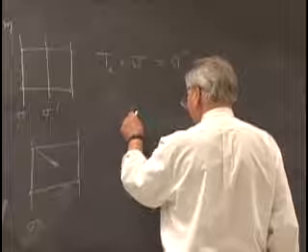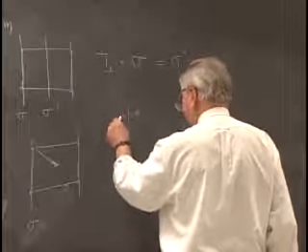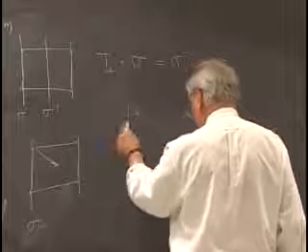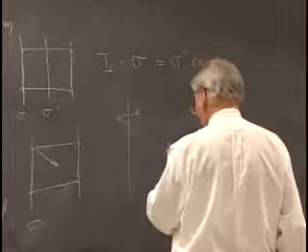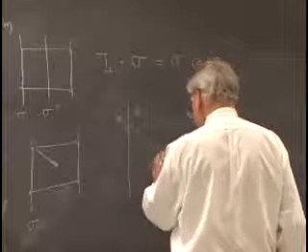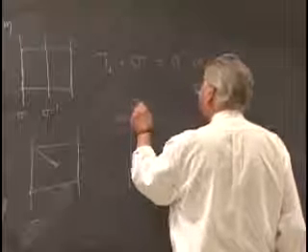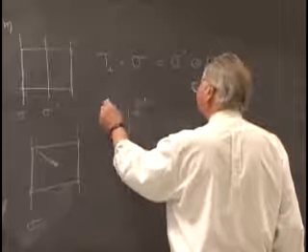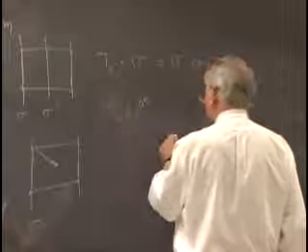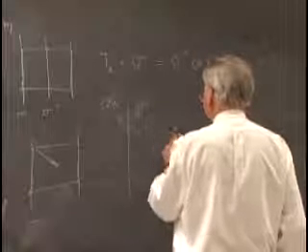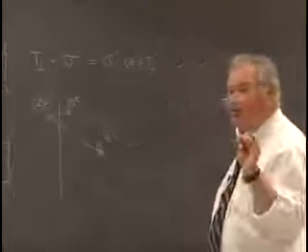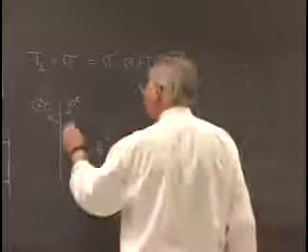If we took an object, reflected it in this plane, and then translated it down to a centered lattice point over here to give us one that sat here, and then asked, how did I get from the first one, a right-handed one perhaps, to a second one that's left-handed, and then a third left-handed one that sits down here? The answer is that we found there was no way we could specify getting from number one to number three in a single shot. We had to take two steps to do it.